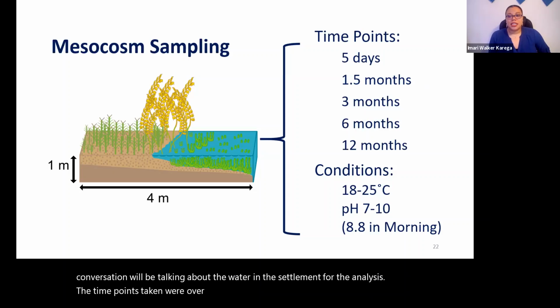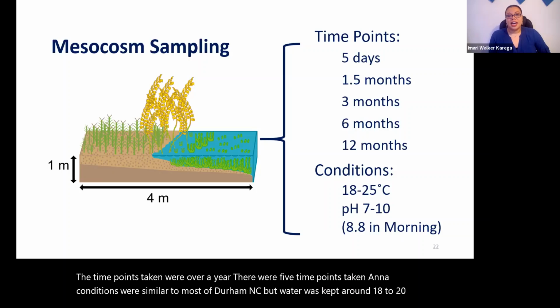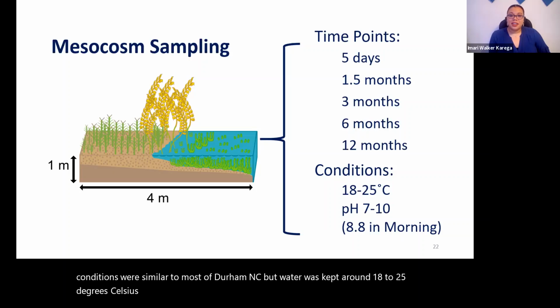There were 5 time points taken, and the conditions were similar to most of Durham, North Carolina. The water was kept around 18 to 25 degrees Celsius, and a pH of around 8 in the mornings when we were actually doing those sampling time points.